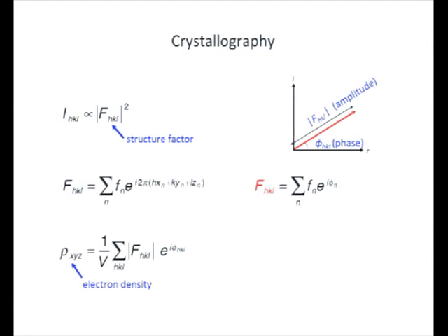Well, we don't have the structure factors. We have the structure factor amplitudes. We do not have their phases. And this is the phase problem in crystallography. This is the problem that has to be solved also in single crystal crystallography.